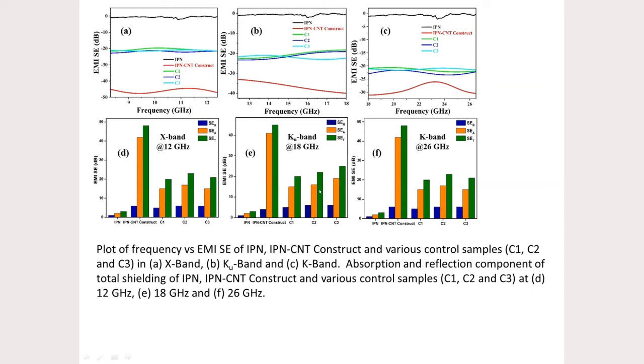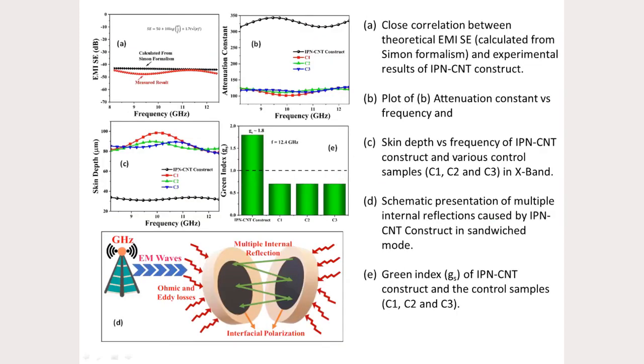And we have measured also the fraction that is reflected and the fraction that is absorbed. And what we have observed here is that in most of our membranes, the absorption is quite high. This is one of the key requirements besides conductivity, that the absorption percentage should be higher, because if it reflects, then it is going to interfere with the neighboring devices. But if it is fully absorbed and dissipated as heat, then we don't have the issue of interference with the nearby devices.